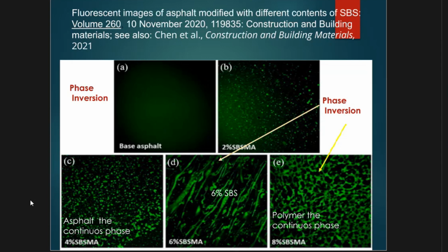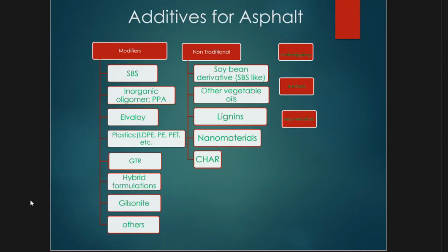one or two SBS manufacturers come up with new polymers. I played with some of them. They're still SBS, but they're talking about the conformation that makes them easy to go in, doesn't make it very viscous, and so forth. So you have that situation of making thinner pavements. But again, the rules for looking at the rheology, you've got to be careful. They probably need to be benchmarked again if the industry is going to grow in the direction of increasing polymer content, right?